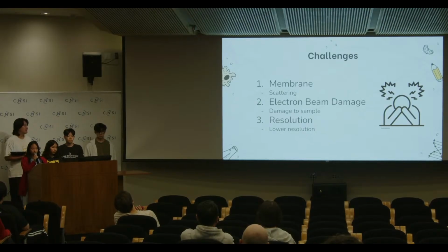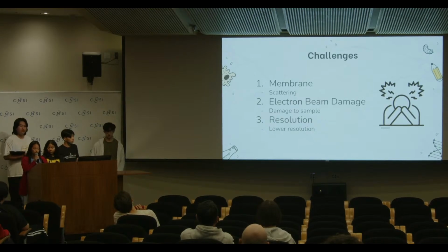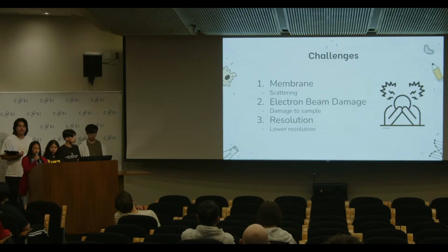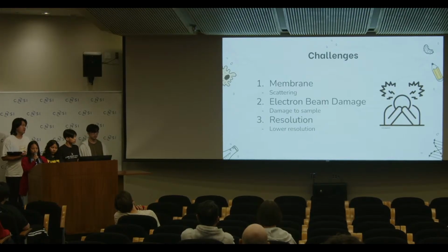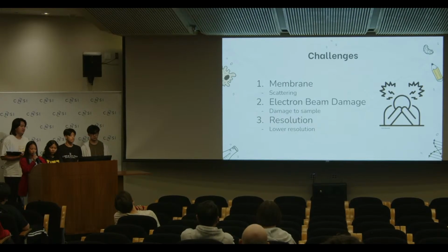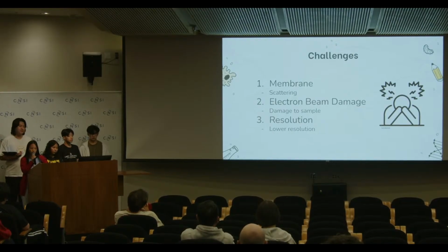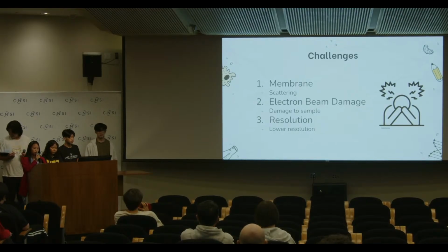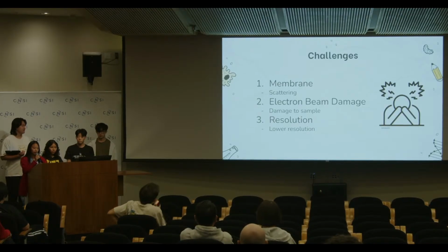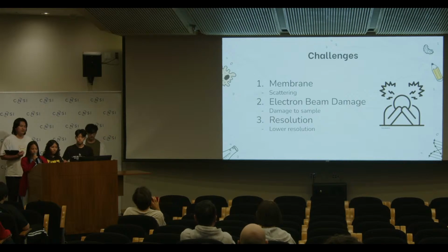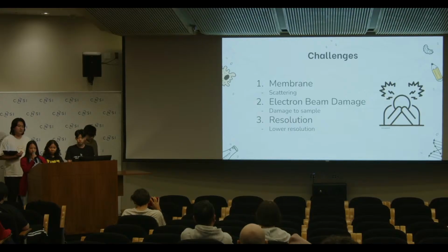There can also be electron beam damage, where the electron beam influences the sample's chemical structure. As the electron beam interacts with the sample, beam damage, or alteration or degradation of the sample can occur. The goal of liquid cell TEM is to observe dynamic processes over time, so continuous and repeated electron exposure increases the likelihood of damage. To check for beam effects, postmortem analysis like MALDI-IMS is done. MALDI-IMS is matrix-assisted laser desorption ionization imaging mass spectrometry, in which the liquid cell is first separated into two membranes, and the sample on the membrane is dried before MALDI-IMS is performed and after a matrix is sprayed.